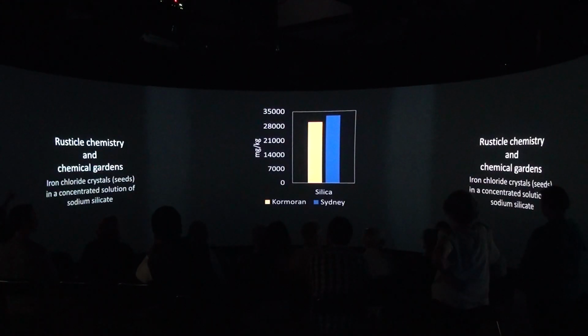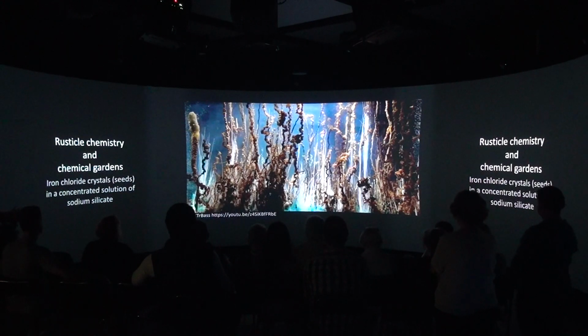chemical analysis that we did to the rusticles was the amount of silica, because it's usually the second most abundant component in the rusticles after iron oxides. So this data just gave me the idea to Google iron and silica, and these appeared. Chemical gardens that, for me, resemble rusticles, just that they are growing from the bottom up, not hanging like proper rusticles. So I kept researching about these phenomena, and it's an iron chloride crystal that is immersed in a concentrated solution of sodium silicate.